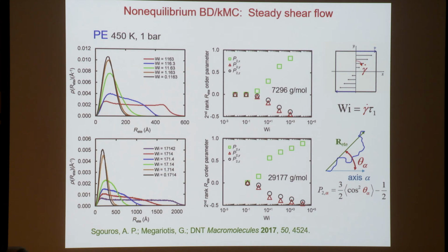Of course, the simulation also tells us why there is this shear thinning behavior. Why do we observe these nonlinear rheological properties? These here are distributions of the end-to-end distances of the chains in the melt when subjected to flows of different Weissenberg numbers for 2 different molar masses. We see that for low Weissenberg numbers, the chain conformations are pretty unperturbed. What we get here for the distribution of the end-to-end distances is close to a Gaussian distribution. However, for strong flows, there is a pronounced unraveling of the chains. The end-to-end distribution becomes much broader.